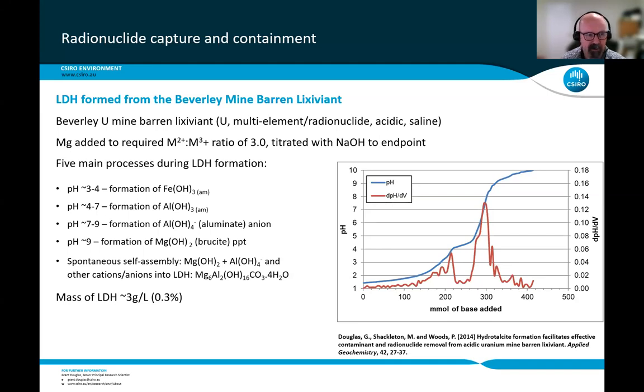pH 3 to 4, no surprises. You start to precipitate out your iron hydroxide as you increase the pH. You start to precipitate out your Al hydroxide. As you increase the pH, though, in this case from 7 up until 9, you actually start to redissolve that Al hydroxide up into the aluminate ion. And then once you get to higher pHs, up to 9 and above, you start to form brucite, which is magnesium hydroxide. Now that's really important.